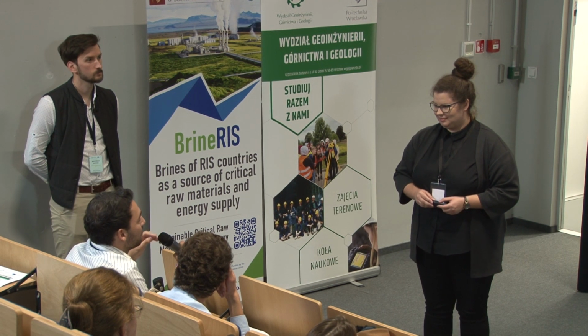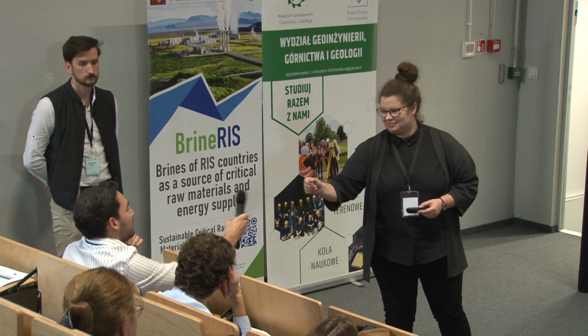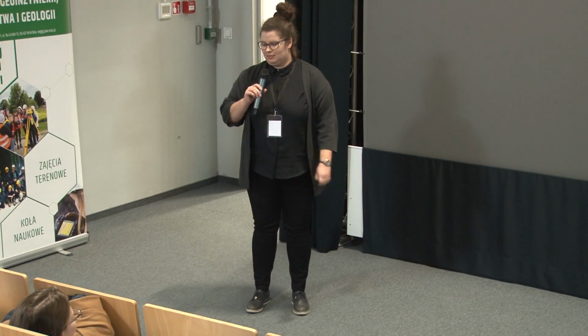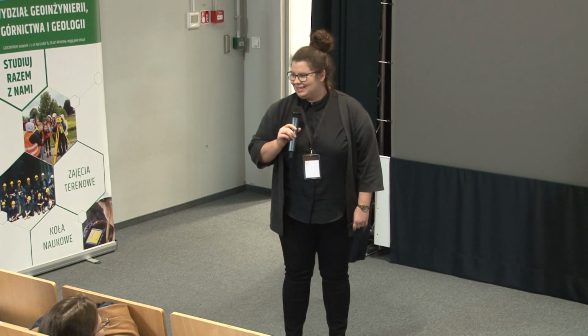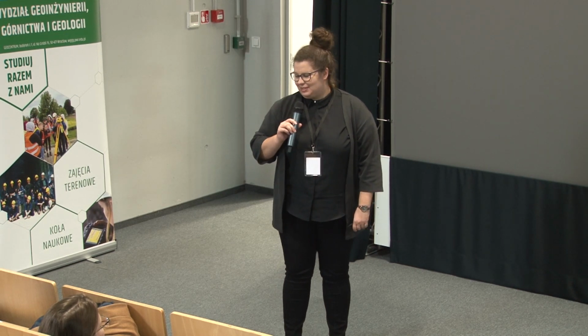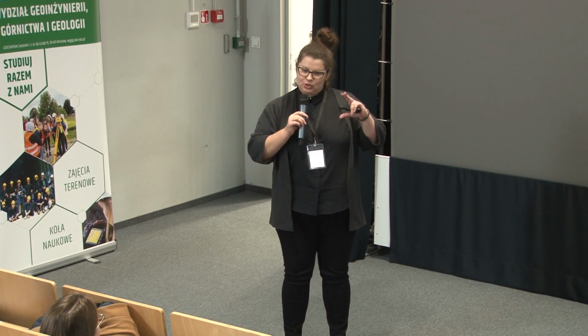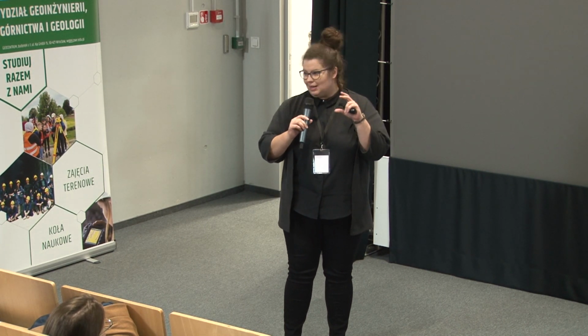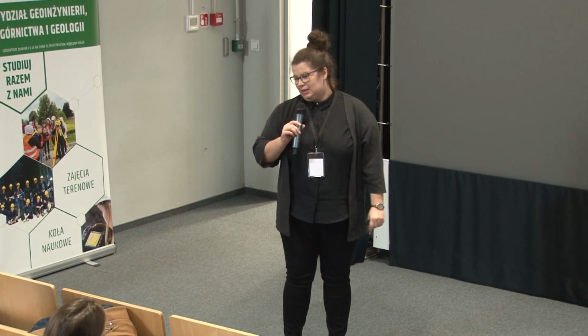During the preparation of the electrodes, what is the binding material that you used? These are stable electrodes, just mixed with a polymer. That's PVC. You apply 10% of the PVC and cast the electrodes. It's extremely thin, 70 micrometers. So the expansion based on the different sizes of the cations could be neglected. So, fine.